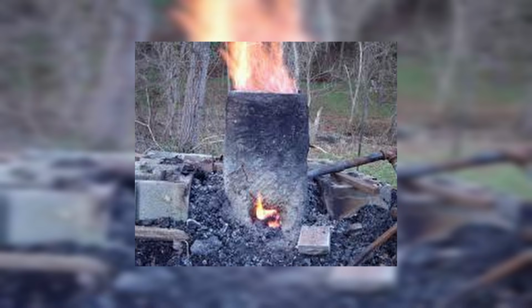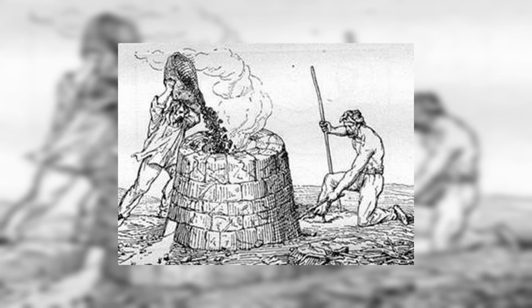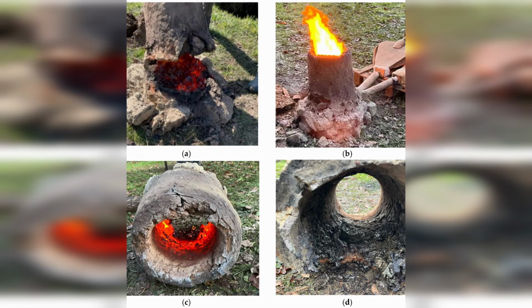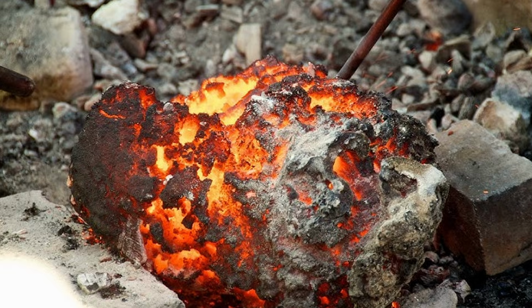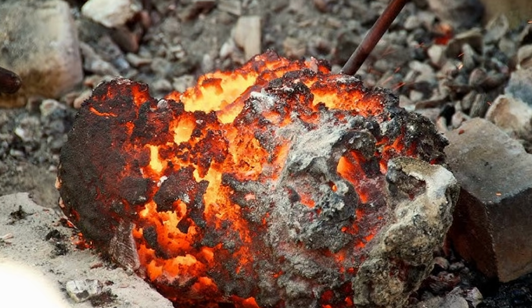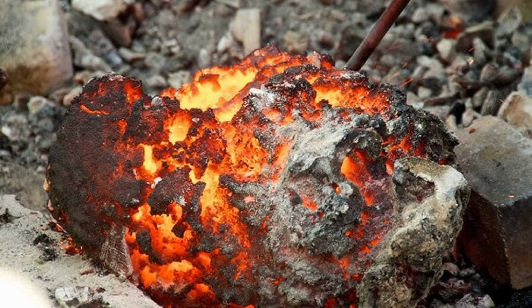What happened instead was a slow, messy process. As charcoal burned, it produced carbon monoxide gas that pulled oxygen away from iron ore, leaving behind particles of pure metallic iron. But all the rocky impurities in the ore, the silica, and other minerals, those did melt. They formed glassy slag that dripped down through the furnace. Solid iron particles sank into this molten slag bath, clumping together at the bottom into a spongy mass called a bloom. After hours of work, the smith would crack open the furnace and extract this incandescent blob that looked more like volcanic rock than metal.